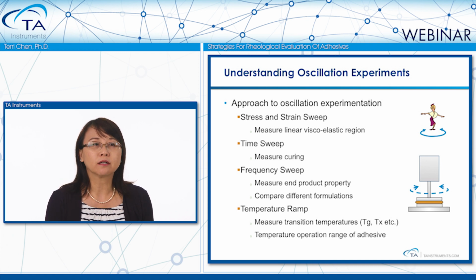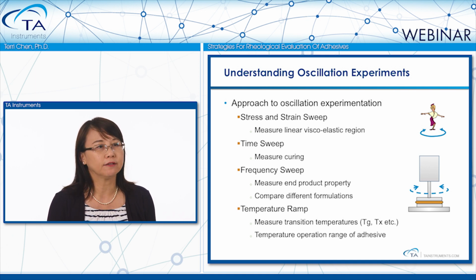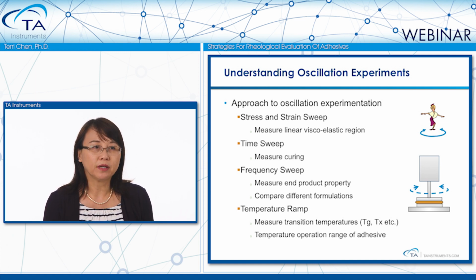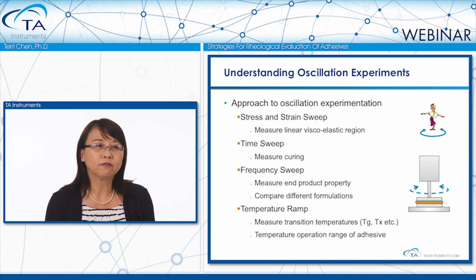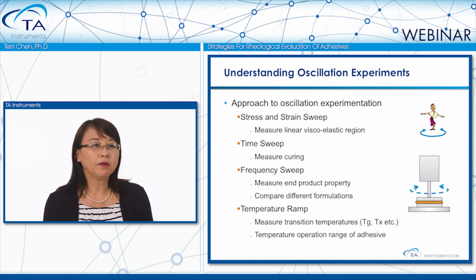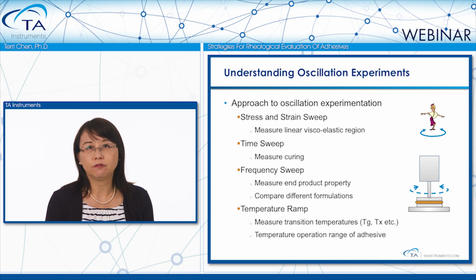A dynamic time sweep is commonly used to monitor curing. The curing can be monitored under a controlled temperature, humidity, or under a certain UV intensity. Dynamic frequency sweep provides direct correlation to the sample's tack, peel, and shear resistance information as a function of frequency or time. A frequency sweep experiment running on a polymer melt sample can also provide information on the polymer's molecular weight and molecular weight distribution. The dynamic temperature ramp experiment is probably the most popular test in adhesive evaluations. It measures transition temperatures and also provides information on the adhesive's operating temperature range.